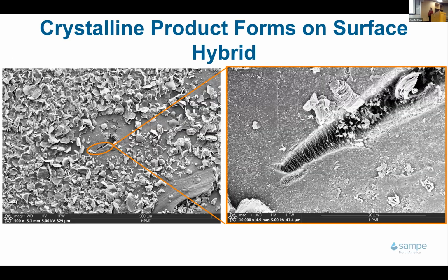So that's not to say that we're without these wonderful little crystals. These little crystals have followed us. But if you can actually see in the char layer, you have this micro crack in the char layer. You can see bridging being achieved across the entire thing. So really nice toughening mechanism, potentially even after these extreme environment events, that is potentially further toughening them. The same kind of crystals that we now know well are species of B2O3.